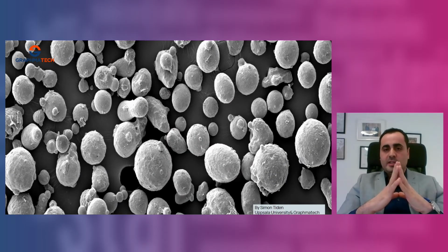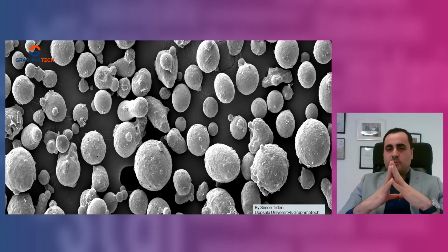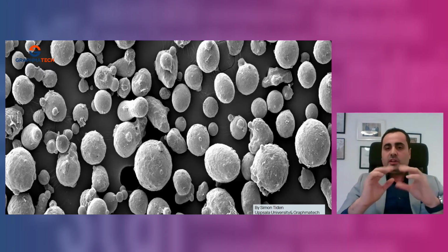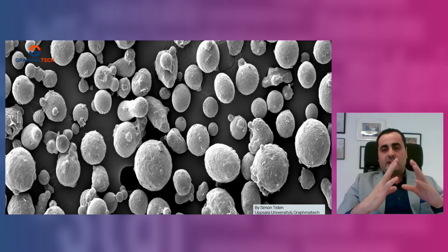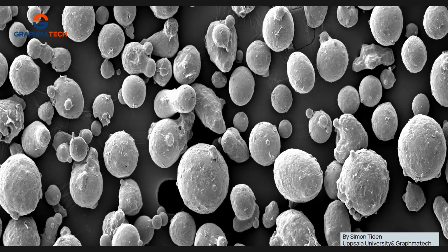And here, let me take you on a journey through the microscope images of one of the alloys. I believe this was aluminum-based, where we coated every individual grain with graphene. And here, I want you to believe me that every single grain has a very thin layer of graphene on the surface. And if we zoom in, things look like this. You have these nice flakes, as you can see, here, here, and there, you are getting the graphene on the surface.